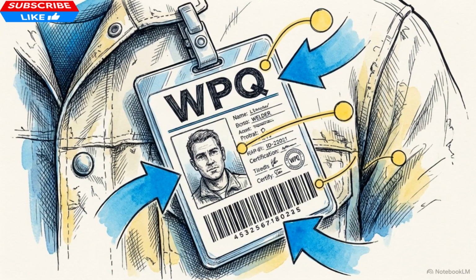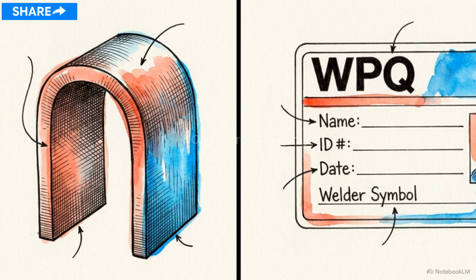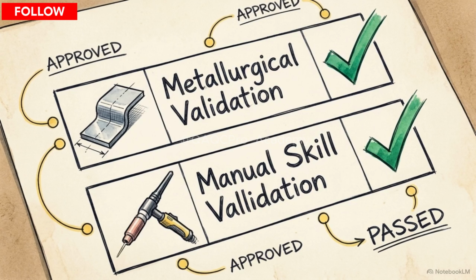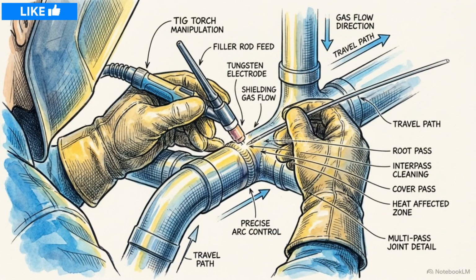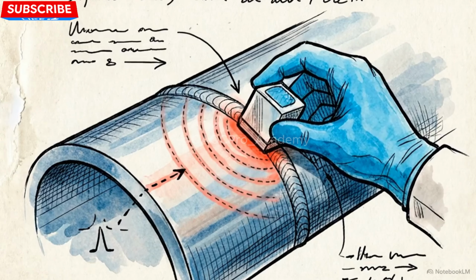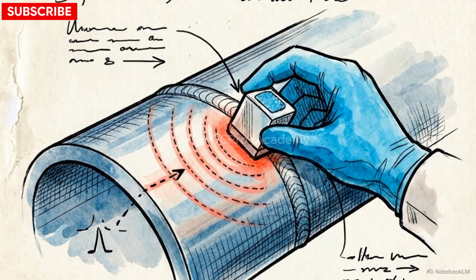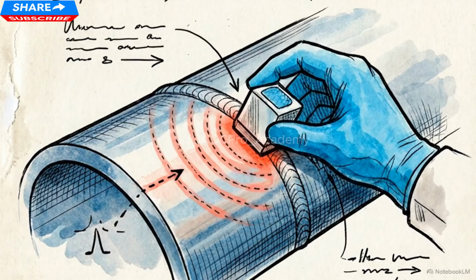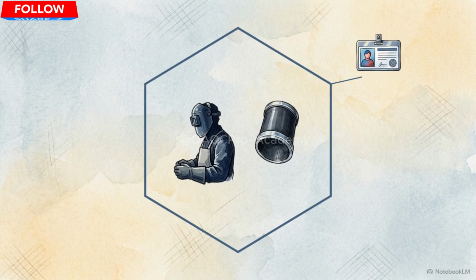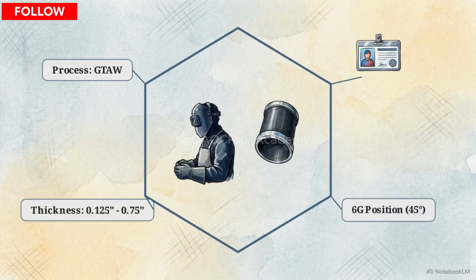While the WPS handles the procedure, the Welder Performance Qualification, or WPQ, proves a specific individual can execute it. Welding the PQR test coupon does not automatically grant a welder WPQ status. The two certifications are separate and require different validation methods. Because the WPQ is a test of manual dexterity, it is typically verified via non-destructive testing. This often involves radiography or ultrasonic testing to confirm the operator deposited sound metal without subsurface defects. The WPQ restricts the operator to the exact process, base metal thickness, and physical position, such as a 6G pipe angle, demonstrated during their test.